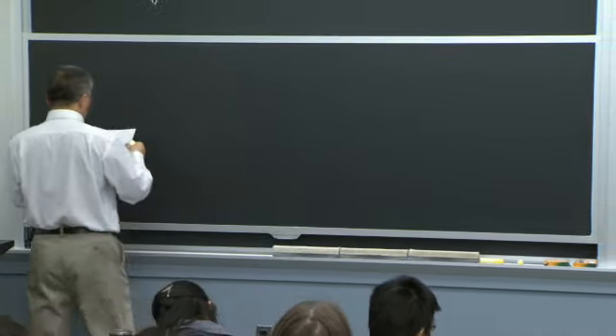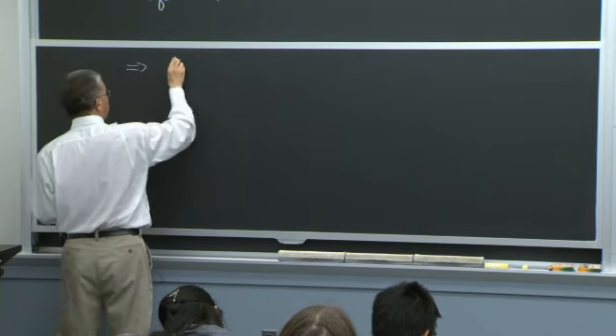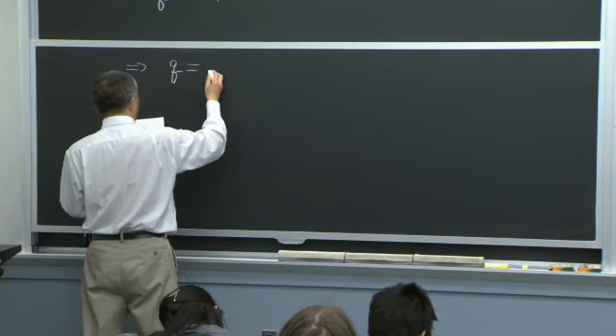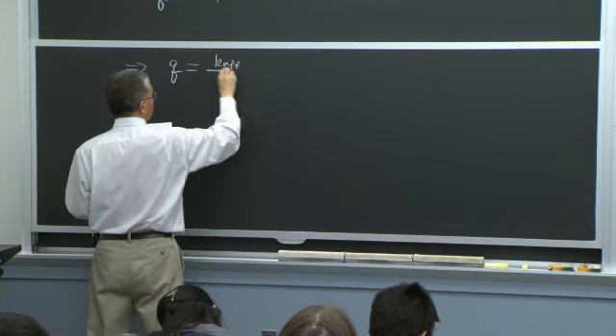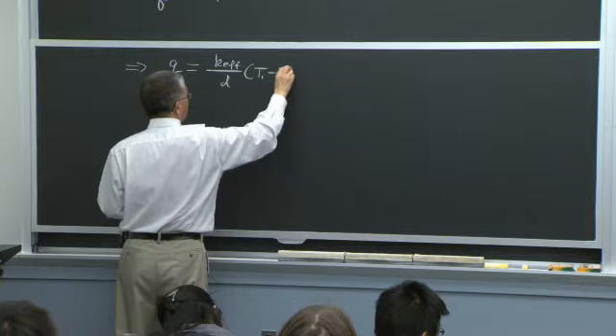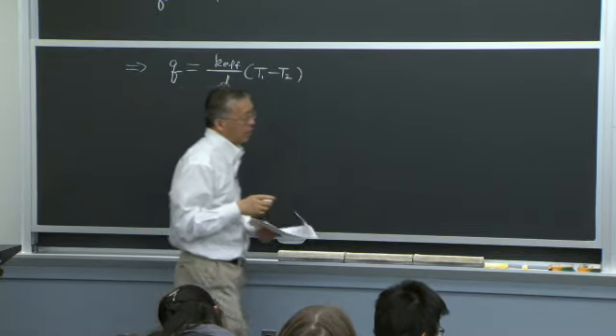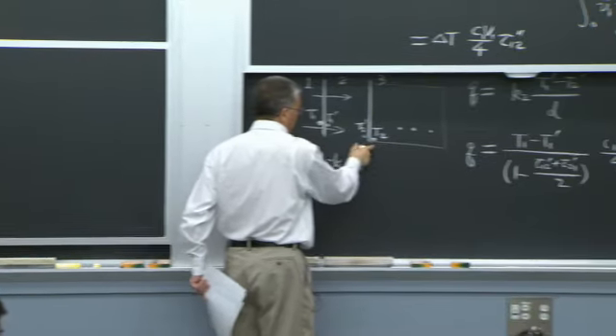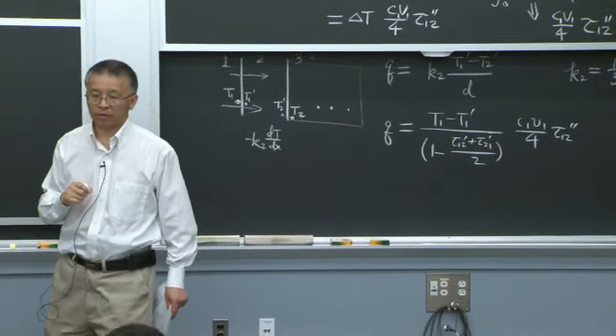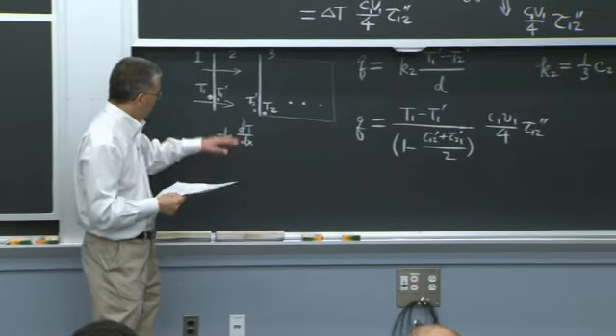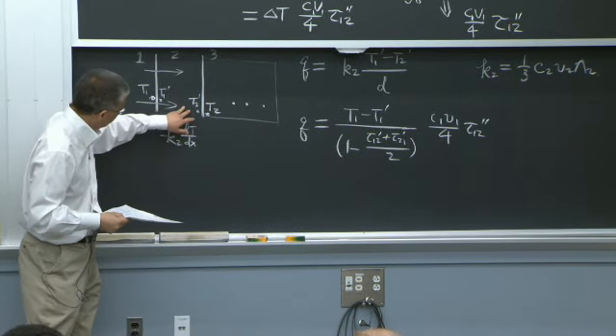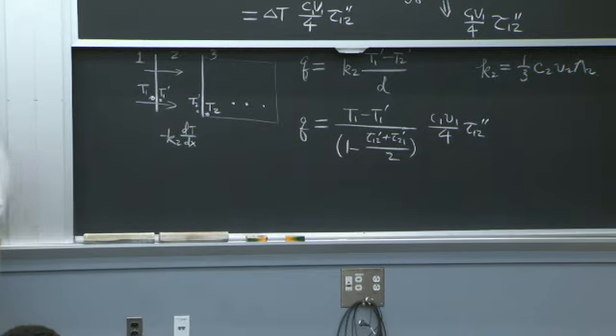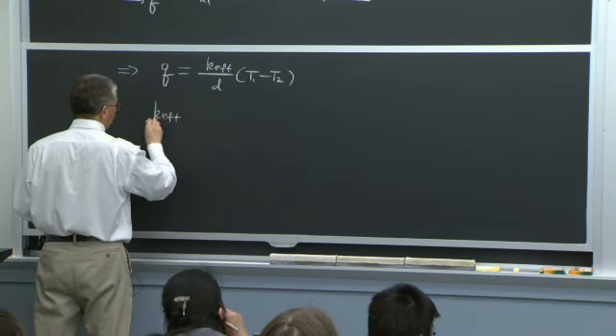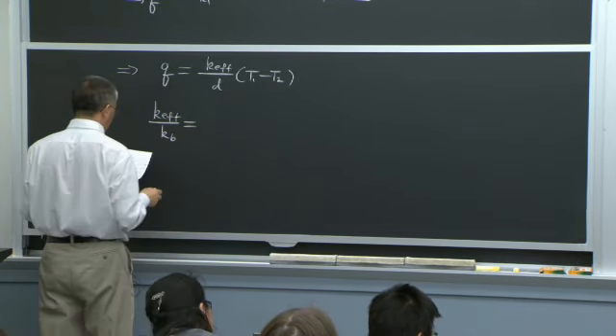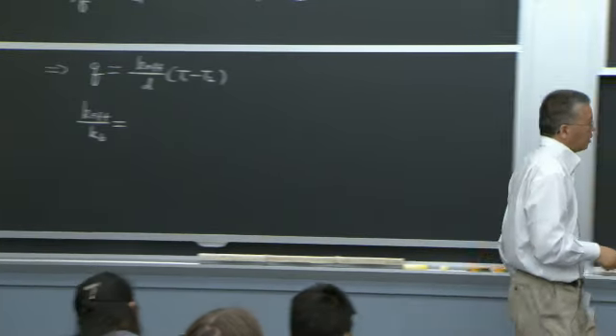So at the end, if you say my Q equals K effective, thermal conductivity over D, T1 minus T2, I'm using the temperature on these two sides. I ask what's the interlayer effective thermal conductivity that includes the conductance inside the layer and the two interface resistances. I add this up together. What I'll have is a K effective, and the bulk, KB, is just K2 here.